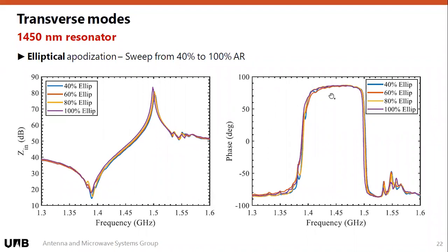You end up not cleaning the modes completely. And you can see this on the phase curves here. So you have still some in-band ripple on the phase. You might not be seeing it in terms of impedance in dBs on the left plot, but on the right plot you see it. And this actually means that your resonator is putting a little bit of energy there. So your resonator, when it is part of a filter, is going to have a little bit of bumps inside. So it's something we don't want.